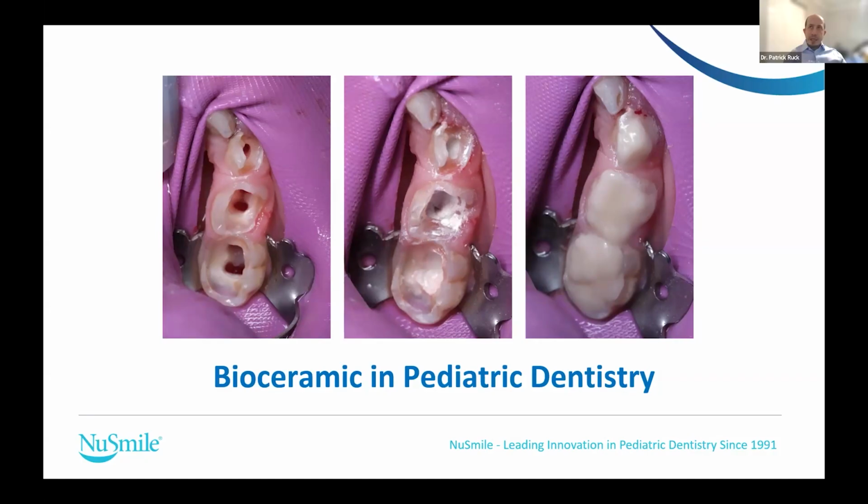When I have looked at all the nuts and bolts comparisons of Biodentine and Neoputty, they're similar, and I could share some of those studies with you. Dr. Primus might be able to answer it too. You're not going to get any difference in performance. When you look at Biodentine, they're di and tricalcium silicate based products. They add calcium carbonate, and there's an accelerant in the liquid.